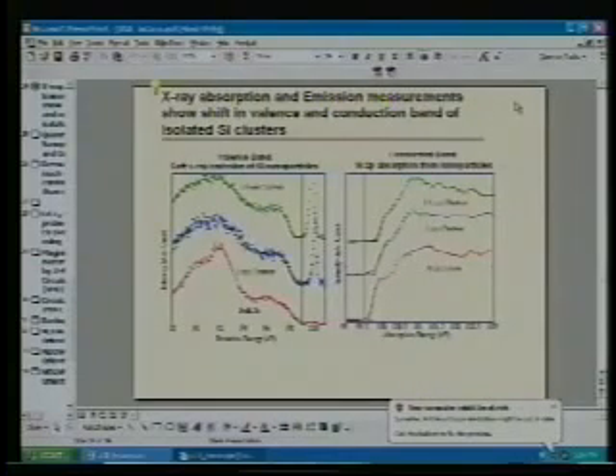So if we look at our structure for our nanoparticles, one of the interesting things here is that at these sizes below 3 nanometers, a lot of the atoms are now on the surface of the nanoparticle. So how do you separate perhaps a surface effect from an actual quantum confinement effect? What you'd have to do in these situations is combine this technique with photo emission probes, where you can extrapolate the bulk component from the surface component in the photo emission.